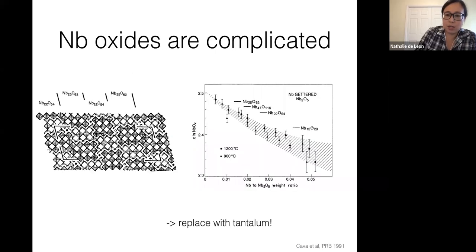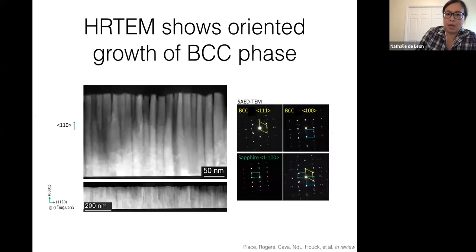Using these really nice substrates, we then trained our eye on what we can actually replace about the material system itself. One of the things that Bob Cava immediately pointed out when we started this project was, why the heck are you guys using niobium? Niobium has the worst oxides in the world. You get all of these really weird substoichiometries, and probably a lot of these are lossy in the microwaves. So his suggestion was to replace it with tantalum, which should have much better behaved oxides.